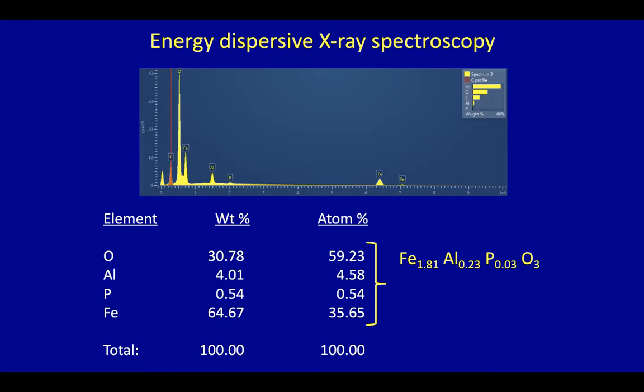And then independently, we collected some synchrotron X-ray diffraction data from this material. And we used a technique called Rietveld analysis to see whether, in fact, aluminum was substituting into the iron position. And there was really no doubt as we were doing our crystallographic refinements that aluminum had to be substituting for iron. And when we did our refinements, we found the occupancies were 89% iron and 11% aluminum at certain sites. And in order to compare our X-ray diffraction results with the microprobe results, you just have to double the numbers that you see for these occupancies.